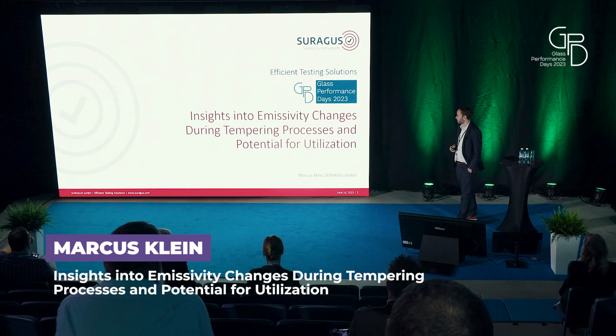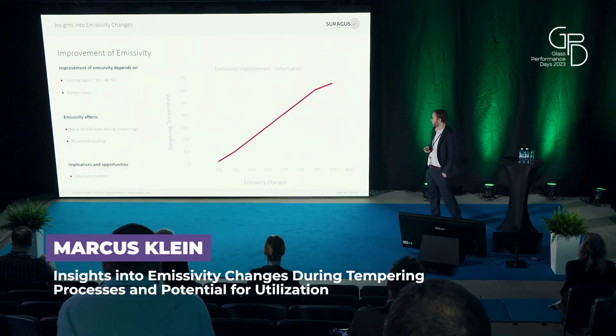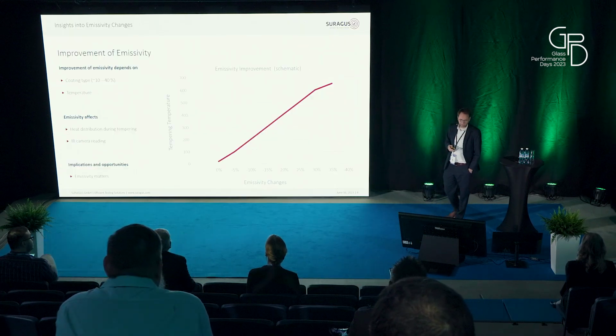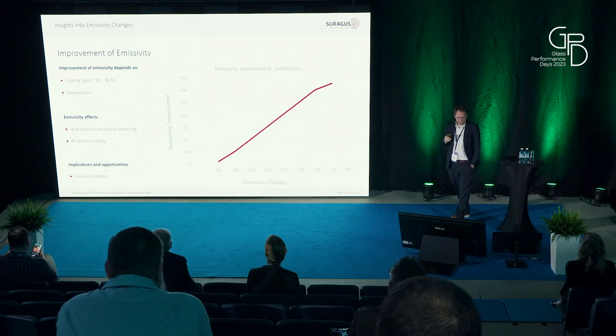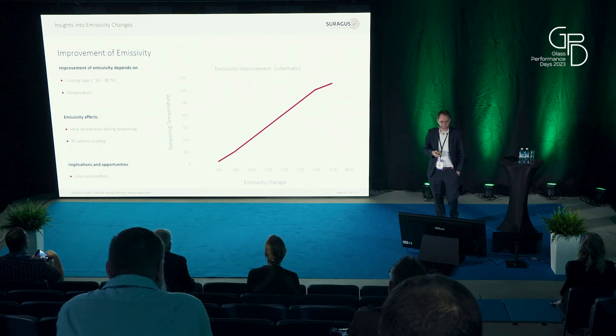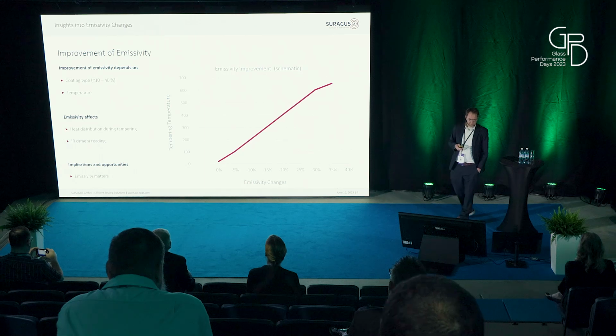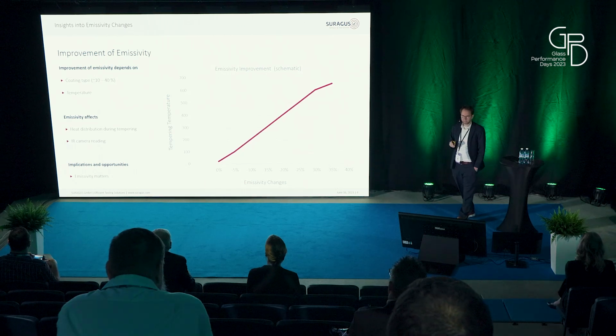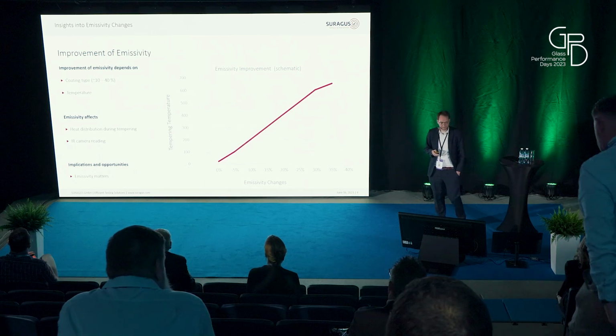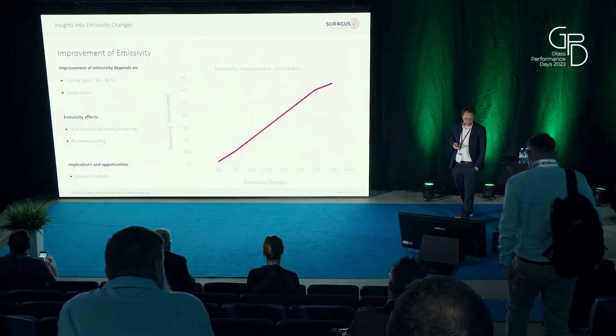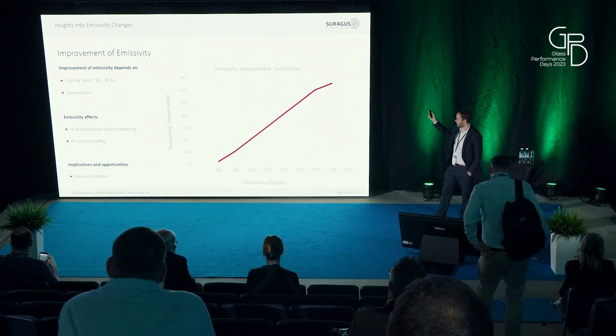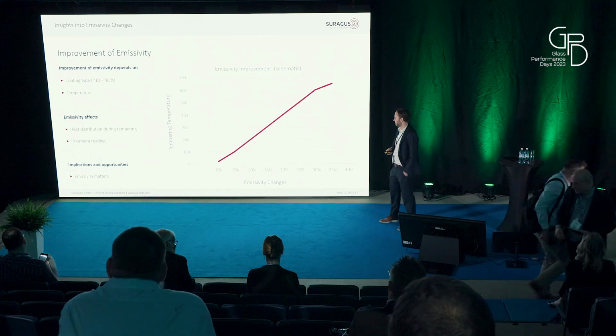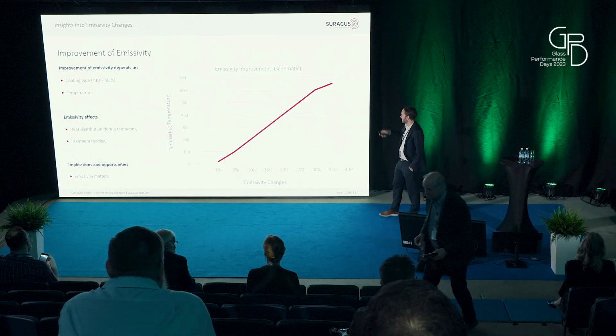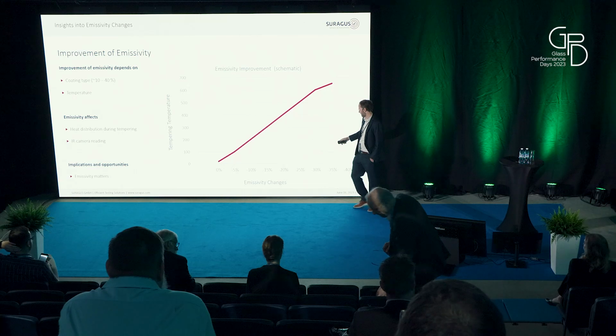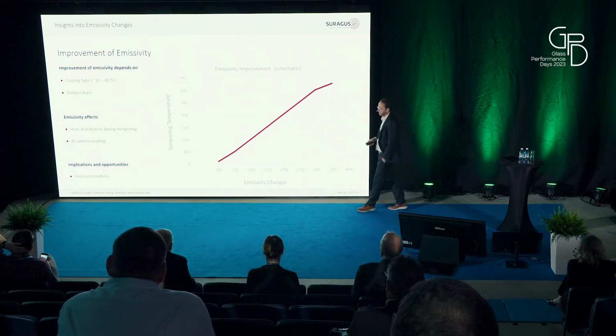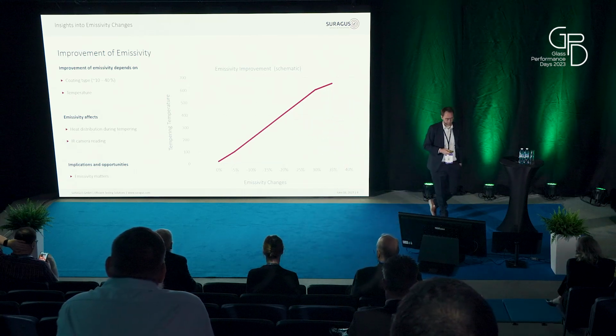Today, we look at emissivity changes during tempering processes, and many people are aware of the effect that the emissivity improves during the tempering process. The changes of the emissivity are from 10 to 40%, depending on the type of glass and of the type of coating, and of course on the temperature. The higher the temperature, the more effect on the emissivity can be observed. This is an example. Some go up to 20%, some go up to 40%. It depends really on the glass and on the coating.